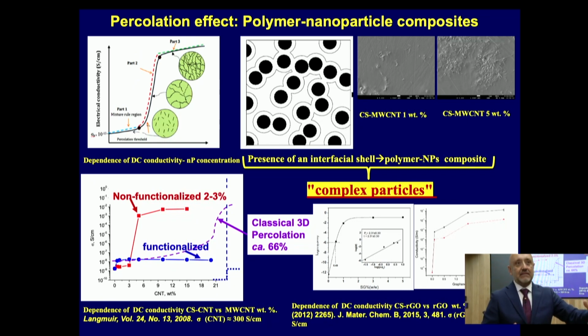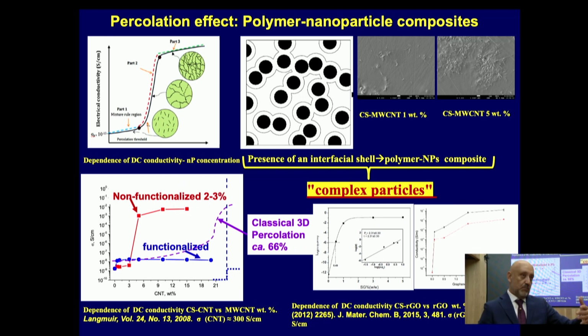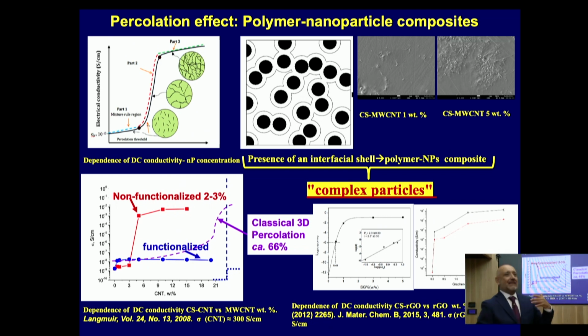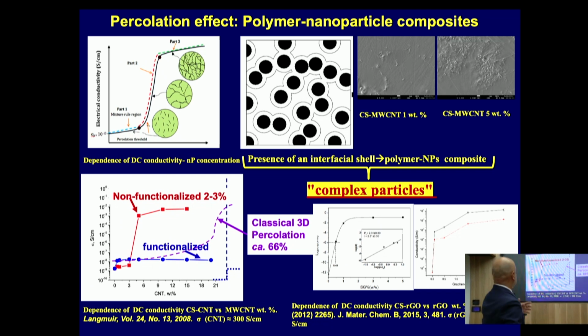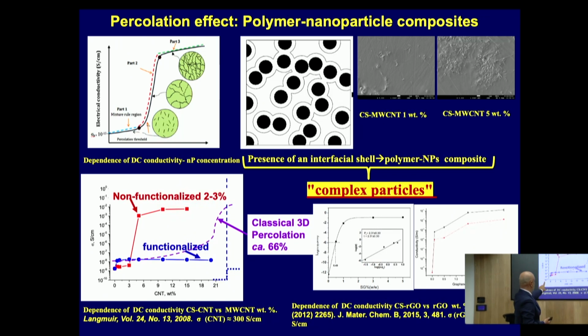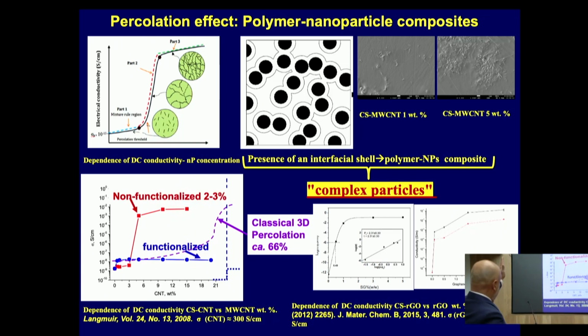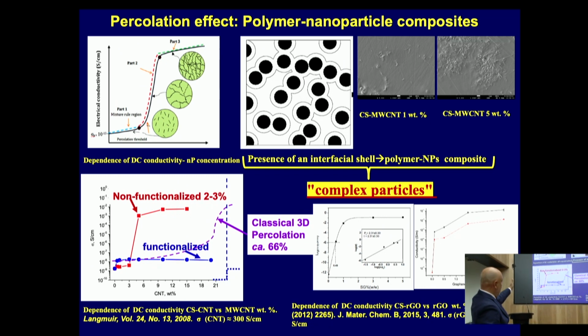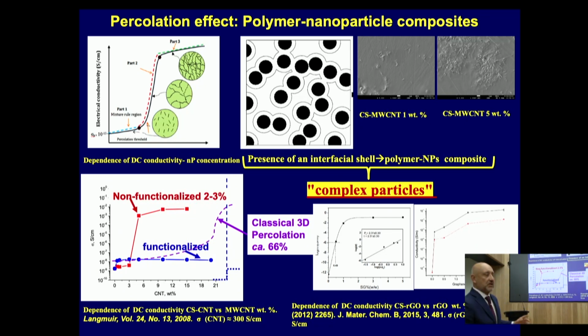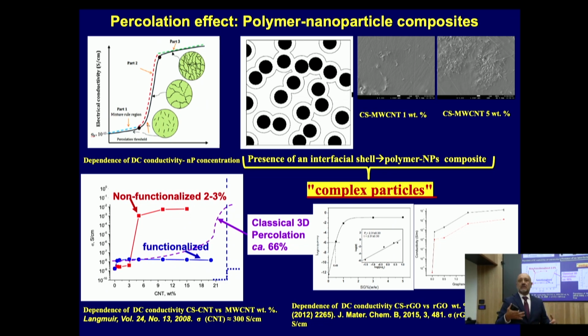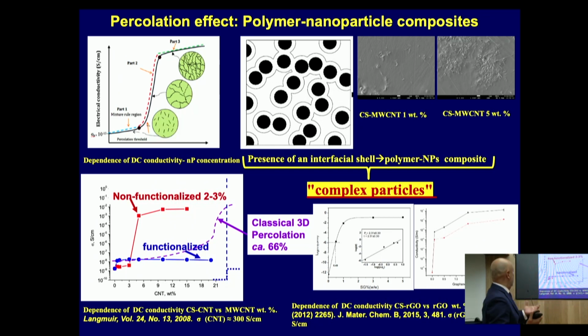And we have taken that theory further. And we have proved it and probed it with different kinds of composites. Now, look at this graph. These are actually experimental data from our laboratories, published in that paper, in the journal. The conductivity is a function of the composition of carbon nanotubes, which are conductive. If we have a matrix that has the proper molecular interactions, such as chelation, cation exchange, or any other different mechanism,